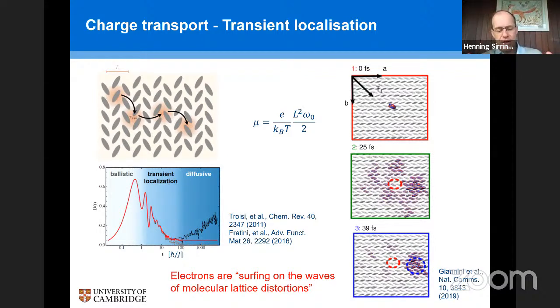At a particular point in time, the charge localizes within that disordered environment of transfer integrals. But then on a picosecond time scale or so, the molecular lattice evolves, and that leads to a diffusive motion of the molecular wave function within that dynamically disordered molecular environment. And so you can essentially think of the electron wave function surfing on the waves of molecular lattice distortion.